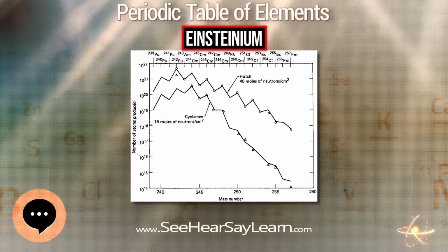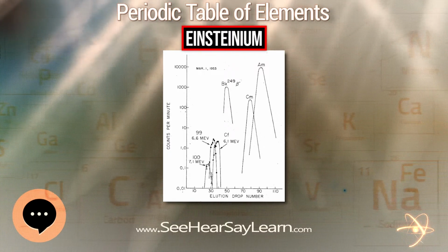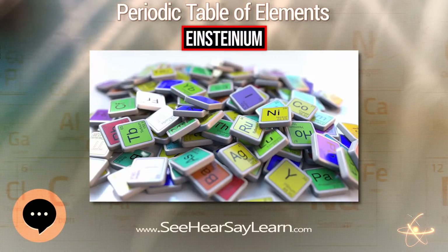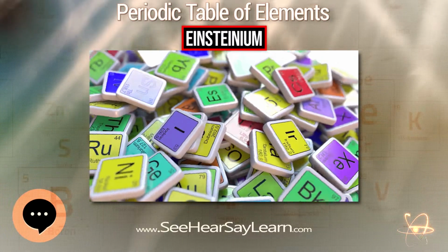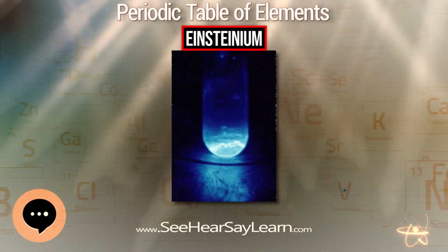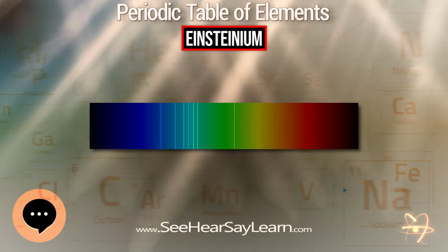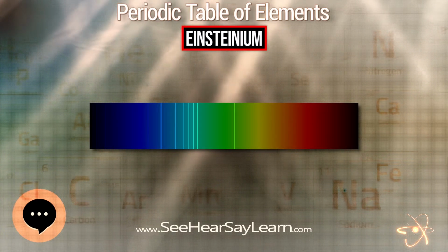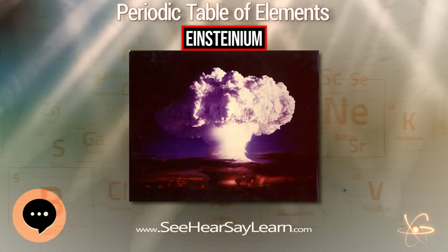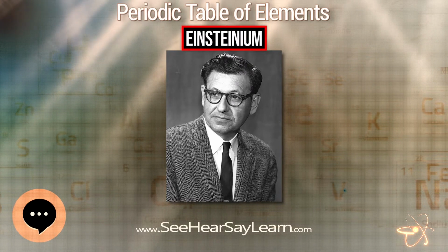The EsF3 crystal structure is hexagonal, as in californium fluoride, where the Es3+ ions are 8-fold coordinated by fluorine ions in a bicapped trigonal prism arrangement. Einsteinium chloride can be prepared by annealing Einsteinium oxide in the atmosphere of dry hydrogen chloride vapors at about 500 degrees C for some 20 minutes. It crystallizes upon cooling at about 425 degrees C into an orange solid with a hexagonal structure of UCl3 type, where Einsteinium atoms are 9-fold coordinated by chlorine atoms in a trigonal prism geometry.